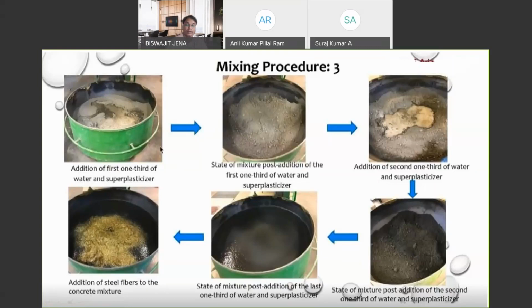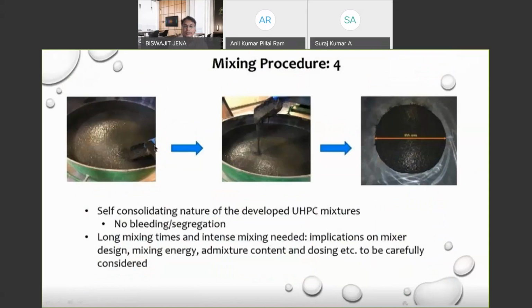So now you add the last 1/3 of water and superplasticizer, and you see the mix being extremely fluid, and you add steel fibers at that time and mix it. So next, the mix obtained is so good that even with that flowability, there is absolutely no bleeding, no segregation, and you see a very cohesive, very dense mix, and it is very hard to believe that this is a less than 0.2 water cement ratio mix. So you need intense mixing, and you need to mix it for a longer period of time at high shear.